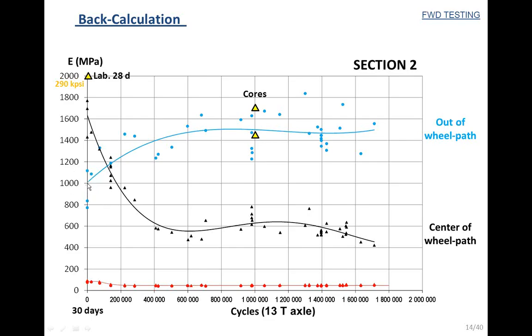This 1000 megapascal modulus is very low for this material. But for sure you can see that there is an evolution along the test. The evolution seems to take place from the beginning to cycle 800,000, 1 million. This is around 1 year. So modulus evolution due to cement curing took place during the first year, which is also according to different references.